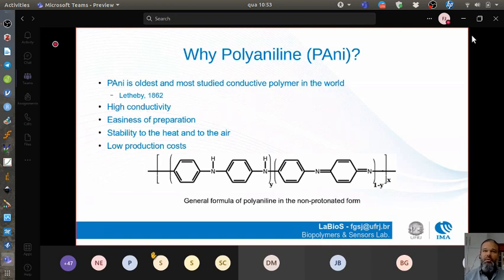Among them, we have the problem related with the poor solubility of this polymer in common organic solvents. Besides this, we have the poor compatibility of polyaniline with the common polymer materials, which lead us to the poor processability of these blends. So most of the time we will work using polyaniline in blended materials or modifying substrates. This second way is very nice because when we modify some substrates, we are using a very small amount of polyaniline, and it is so good as I will show you in the next slides.